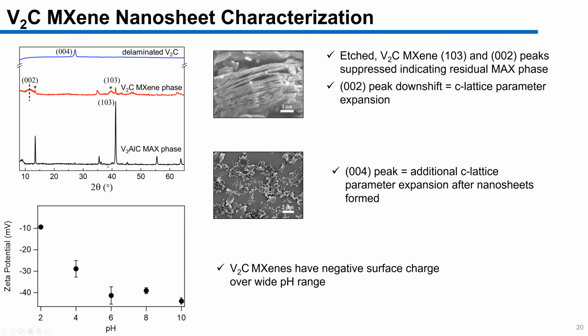And when there's no atom nearby as the X-ray is scanning your sample, you get the baseline here. If you do this enough for a lot of inorganic materials, you can build a reference library, which you can use to match against the sample you're trying to measure. So we use this X-ray diffraction technique for the MAX phase material to verify that our starting material had been synthesized properly. And when we do the etching steps and the nanosheet formation steps, we achieve spectra comparable to what's been observed in the literature by others who have also performed X-ray diffraction. This information of peak shifting and stretching and peak suppression, we can use to gain information about how the crystallographic structure of the vanadium carbide is changing with respect to the different treatment processes.